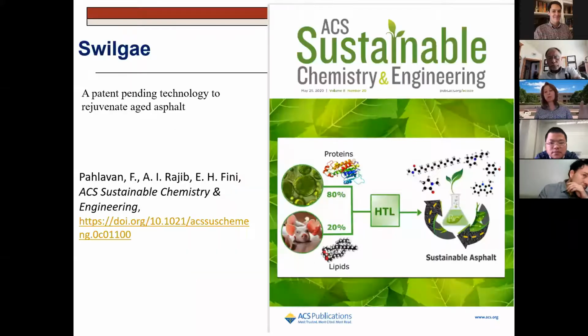Here in the 4:1 ratio, we did many different scenarios, and this has a combination of protein and lipid. I don't want to go into the biology side of things, but we managed to create this, and this paper made it to the cover page of an ACS journal. It talks about how, if you can get a combination of protein and lipid, you can make a rejuvenator which is highly efficient, because all those molecules can diffuse in and break aggregates. In that sense, we have the science and the tools to make the rejuvenator the way we want. And if we can get those from biomass, which happens to sequester carbon from the air, now you are killing two birds with one stone, because your rejuvenator is effective. And by the way, you actually sequester carbon from the atmosphere into those.